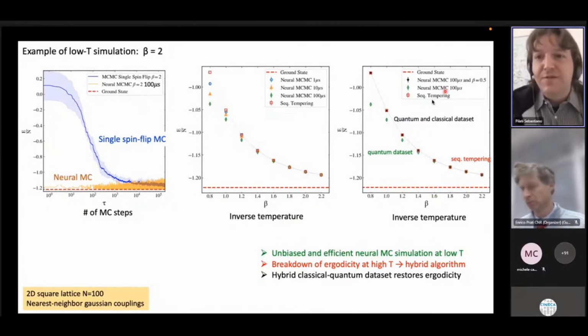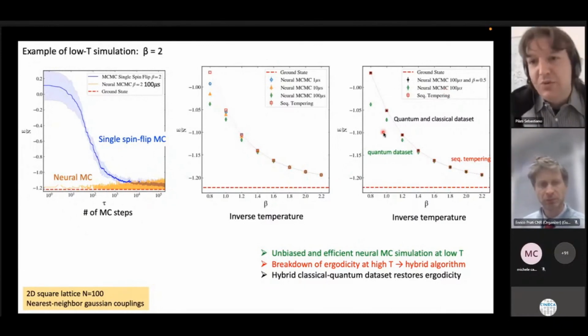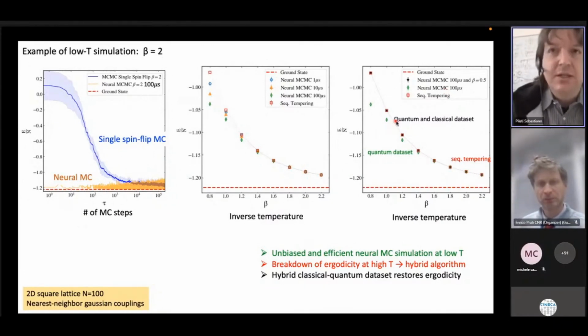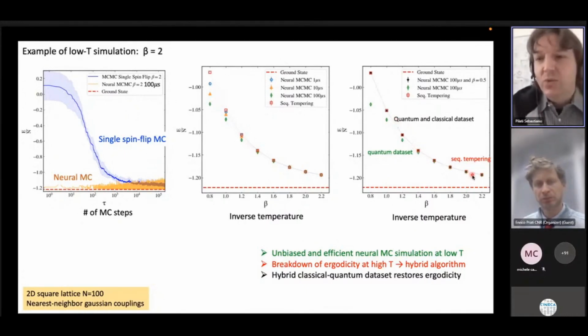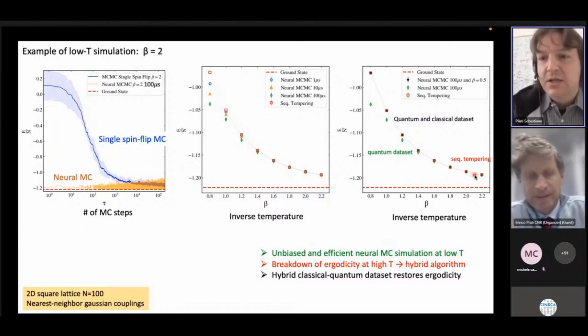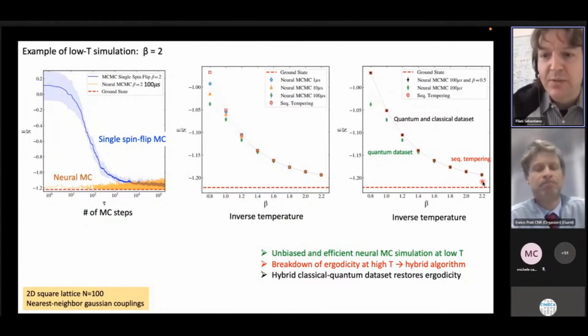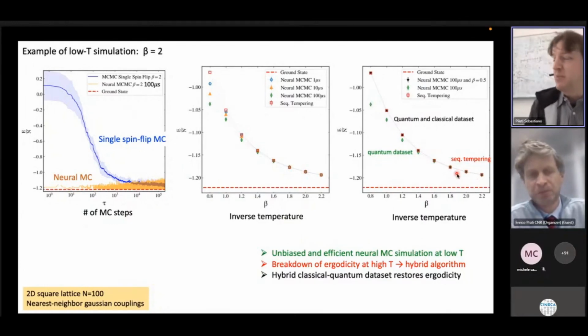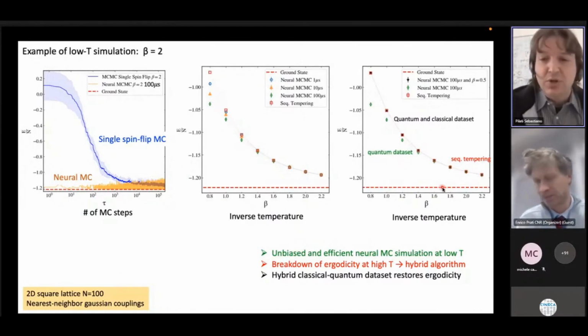But this is a problem that we can easily fix by using a hybrid approach where we combine the quantum data obtained from the quantum annealer and classical data obtained with a classical Monte Carlo simulation performed at high temperature. And when we train the neural network on the hybrid data set, this allows us to perform an efficient simulation, with the black color, which is unbiased at all temperatures, both low and high. So this hybrid approach allows us to perform an efficient neural Monte Carlo simulation at any temperature.